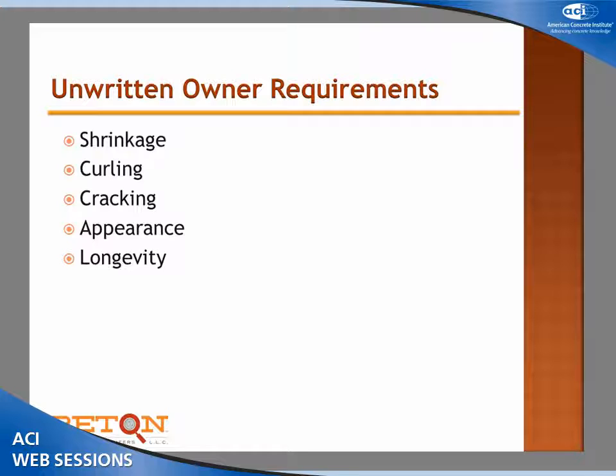We go on and look at this process. If the ready-mix producer is being held responsible for a 100-year design life, guess what I have to control? I have to control, for chloride ion corrosion, two things: the permeability of the concrete and the clear cover. Because if I have very impermeable concrete and the steel is only up a quarter of an inch below it, I probably won't get what I want.